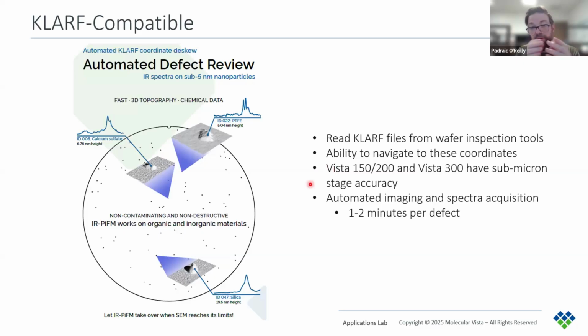So as the critical dimensions continually decrease in the semiconductor industry, the effectiveness of EDS for identification will be more limited as we become more interested in these smaller and smaller contaminants. So this is where PiFM can fill that gap.